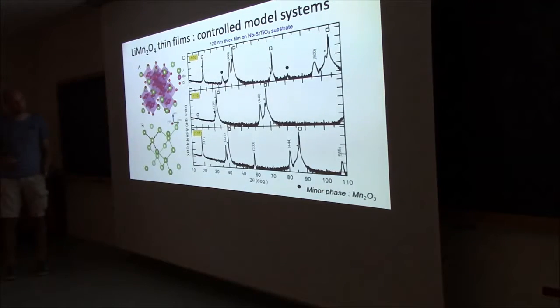So if you check this in X-ray diffraction, you can see the peaks of the substrate with the squares, and you can see that the peak next to it, that's where you have your spinel material. It always has the same orientation as the substrate. And it nicely forms this spinel phase. Except for the one with the 100 orientation. There you see 2 extra peaks, which is a minor phase of manganese oxide. And we think that's from these truncated pyramids where you have a top surface, which is 100, where it can much easier release some lithium. So that's where you create some of these phases probably.